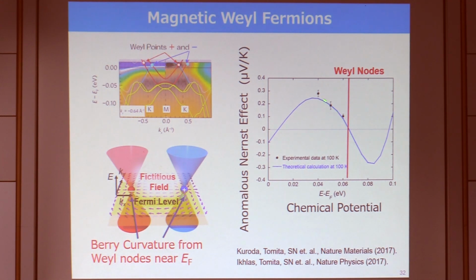And this is a rather dramatic change. It almost becomes half, and this chemical potential shift is made by just a few percent manganese doping change. So this is a rather drastic change. This also tells us that there is a large Berry curvature from the Weyl nodes. And we also confirmed by using ARPES measurement that the band structure is consistent with the DFT calculation.